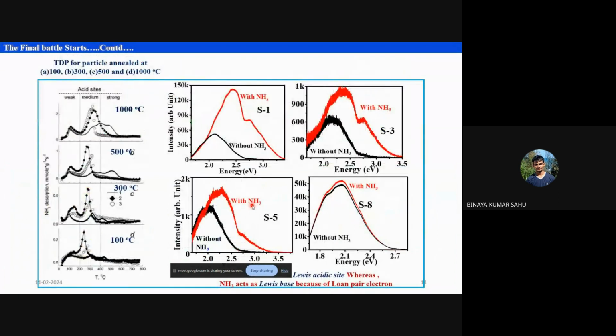The bigger particle, this 25 nanometer particle, also contains lots of oxygen vacancy. Okay, and it also should show some sort of increment in the blue region, but that is not happening. So this behavior is very specific towards the smaller material, but this never happened for the bigger material. So I have to turn down this mechanism. This mechanism is not correct, because if it were true, then I should see a PL spectra enhancement in the blue region for the 25 nanometer particle also. But that is not happening. So I cannot believe this mechanism.